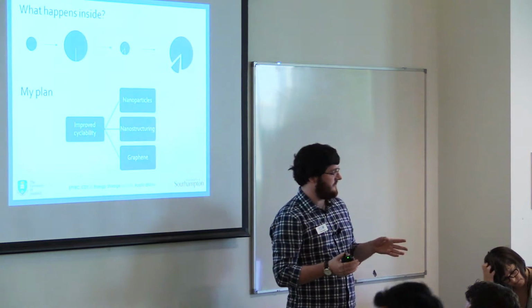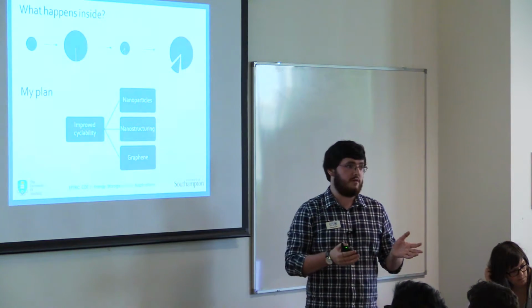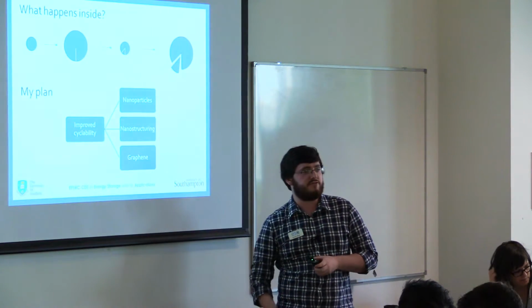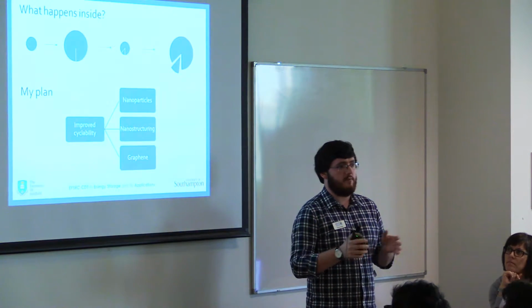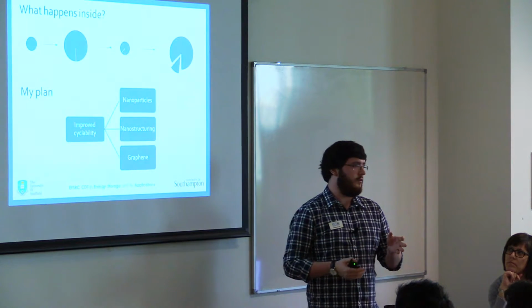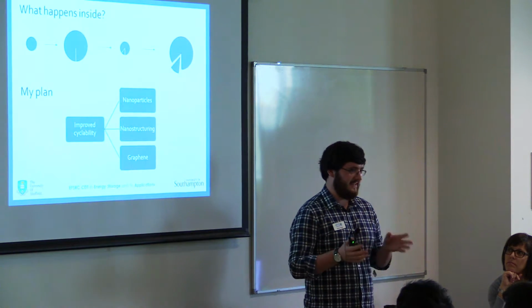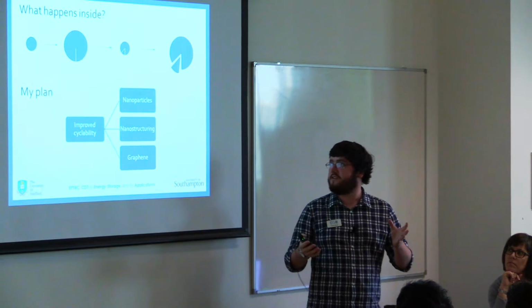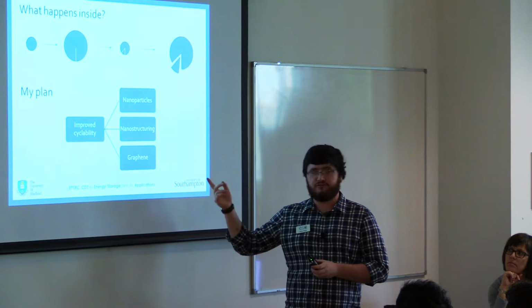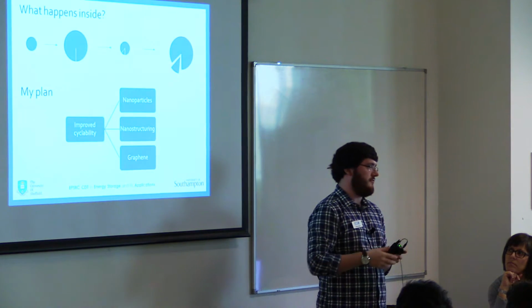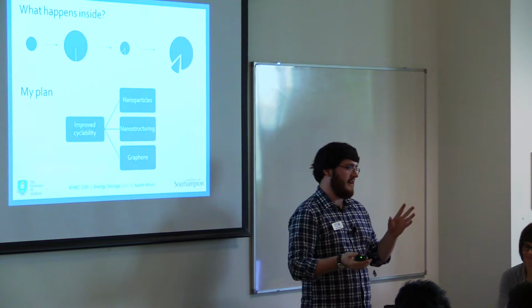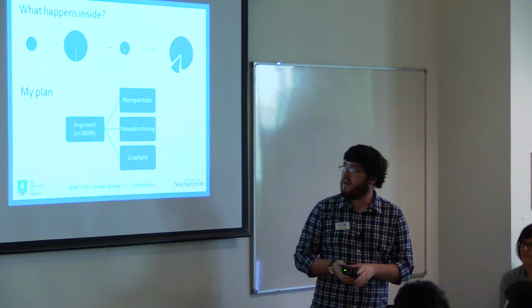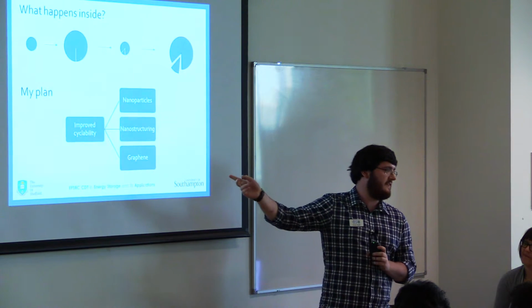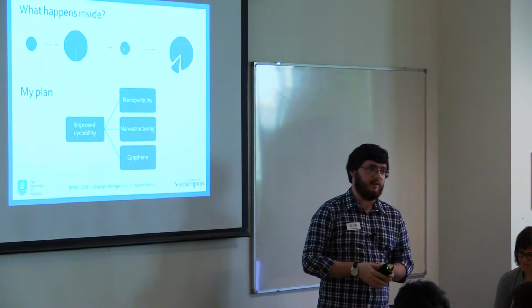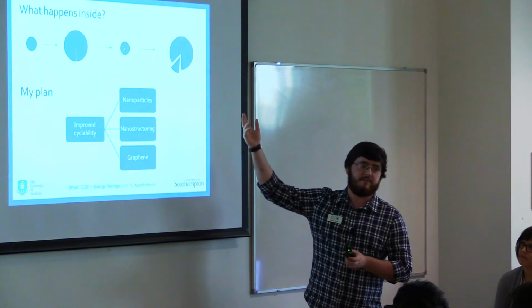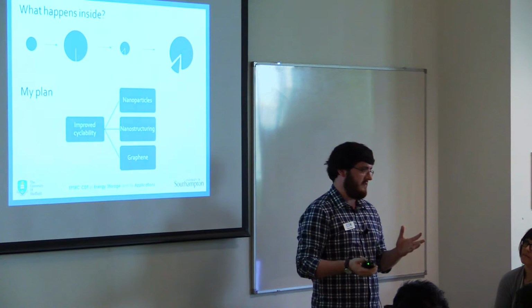So my plan is to improve the cyclability of the silicon electrode, starting with nanoparticles. If you reduce the size of your silicon to begin with, you can better accommodate the volume expansion. The graph I showed before did use silicon nanoparticles, so as you can see, that is not a good enough option at this moment in time. So I'm going to move on to nano-structuring. You might be aware of some nanostructures that already exist, nanofibers, silicon nanotubes, that kind of thing. And then finally, as suggested in the title, I'm going to include graphene, and hopefully that will improve the interconnectivity within the cell. Even if cracks do occur, potentially we won't lose as much material.